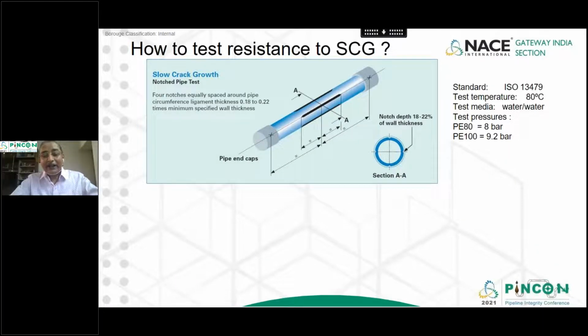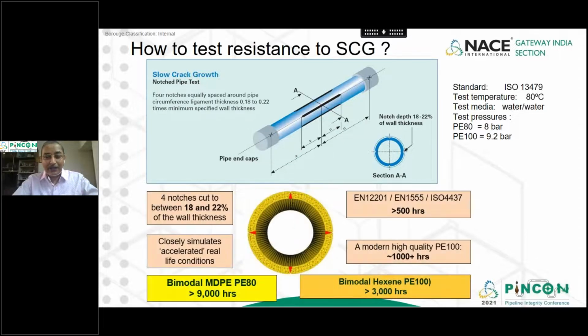They are done by cutting 4 notches on 4 sides of the pipe, typically 18 to 22% of the pipe thickness will be the notch depth, and then 80 degrees centigrade water is put inside, and they are also put in the outside water test media at 80 degrees centigrade, and there are different pressures employed for P80 and P100. Now, EN and ISO standards require failure time of more than 500 hours.